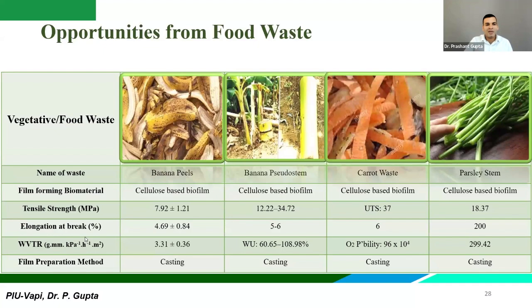So you can see here, this is the name of the waste, the film forming biomaterial, the tensile strength, elongation at break, water vapor transmission rate, and the method by which the film is made. Everything is reported in research, and people have worked on this and proved that it is possible. Banana peels, we all know, and banana pseudostem especially is very rich in cellulose. One banana plant only gives fruits for one season. So what they do is cut it, allow it to dry, and then burn it, right? Rather than that, you can extract cellulose and make films using casting techniques.